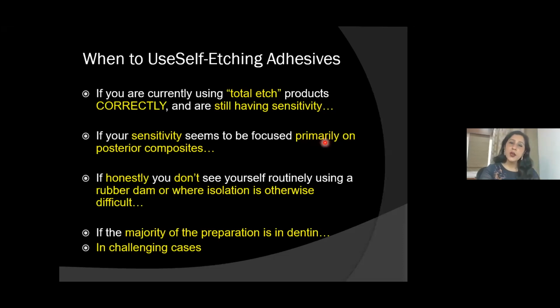If you're currently using total etch products correctly and still having sensitivity, if your sensitivity seems to be focused primarily on posterior composites, if honestly you don't see yourself routinely using a rubber dam or where isolation is otherwise difficult, if the majority of your preparation is in dentine, and this is what I want to focus on. In challenging cases where you cannot reach, where you have less time, and in patients who do not open the mouth very well, where thorough isolation for a longer time is difficult, in all these cases, you can switch to self-etch adhesives.